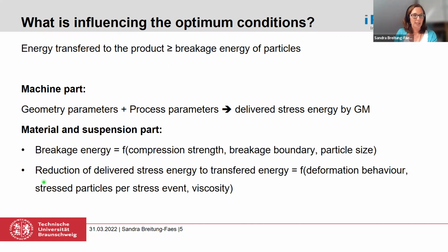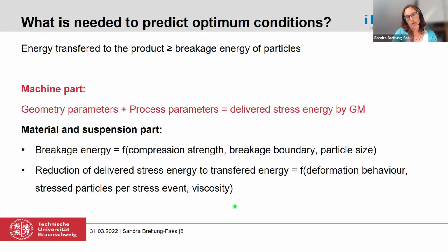And when we go here first to the second point, because I came from the machine part, we will have some reduction values within our equations, which reduce the transferred energy. And these are a function of the deformation behavior of the material and the grinding beads in relation to each other. These are values like how many particles are stressed per stress event, because especially when you go to very fine particles, you can assume that more than one particle is stressed during a stress event. And we have the viscosity, which may play a role. So I would like to start by introducing what I thought about the geometry parameters, and then I would go on with the material and suspension part.